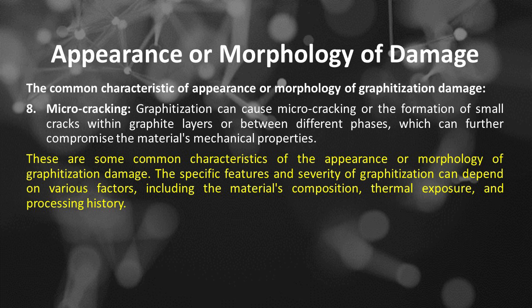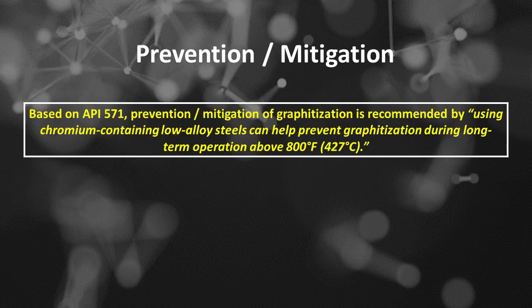The specific features and severity of graphitization can depend on various factors, including the material's composition, thermal exposure, and processing history. Prevention or mitigation. Based on API 571, prevention or mitigation of graphitization is recommended by using chromium-containing low-alloy steels, which can help prevent graphitization during long-term operation above 800 degrees Fahrenheit (427 degrees Celsius).